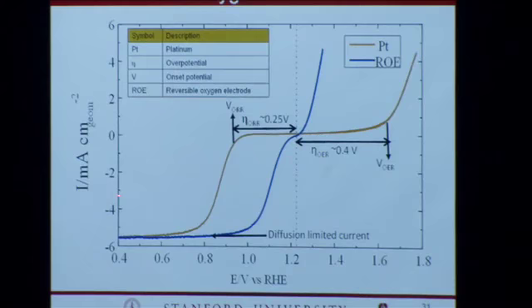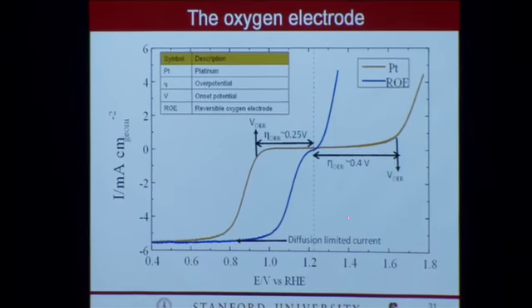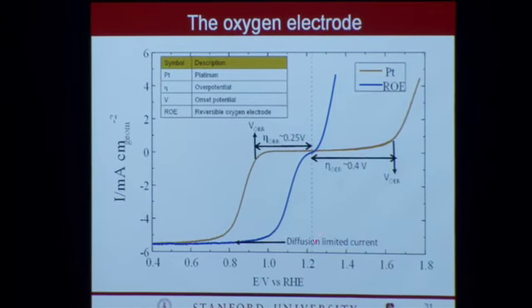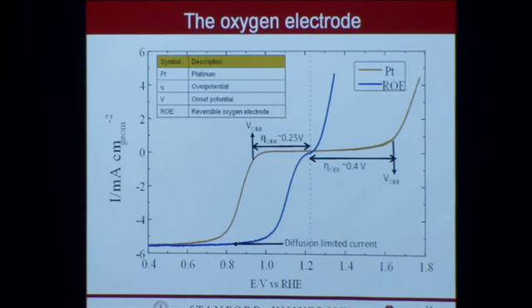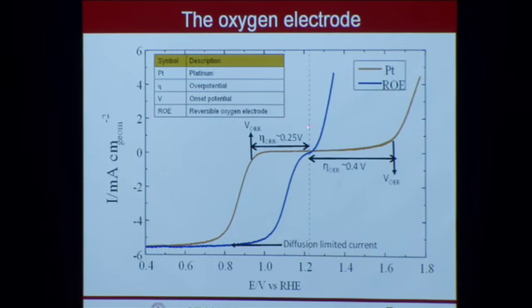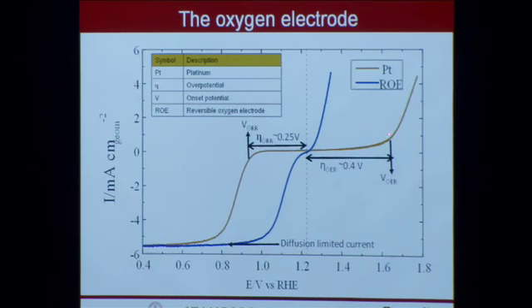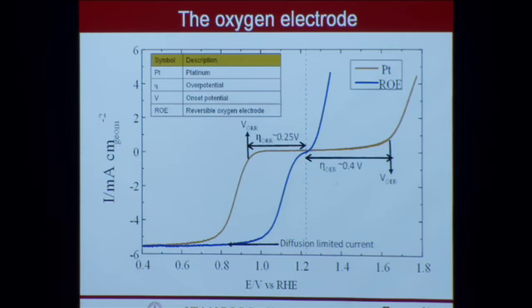This is a current voltage curve with the equilibrium potential here pointed out for oxygen electrochemistry at 1.23 volts. That means if you're to the oxidation side, if you're on the positive side of 1.23, you're going to favor water oxidation to O2. If you're on the left side, or the cathodic side of that equilibrium potential, you're going to favor O2 going to H2O. Zero current means that nothing's going on. If you see a negative current, that means it's a reduction current.